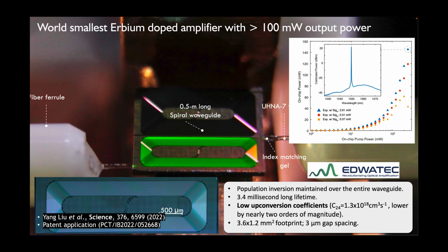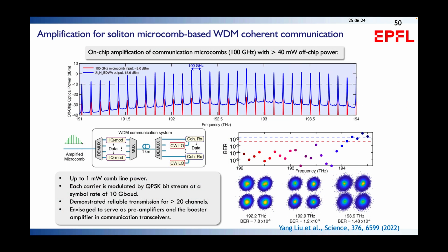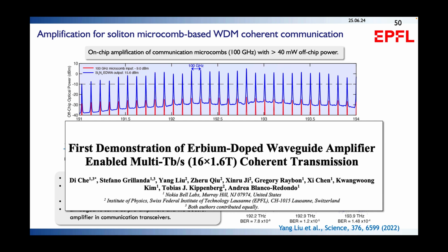Now, where could you employ such very compact Erbium amplifiers? One application is pluggable optics for data centers and data center interconnect, where also you need to amplify the optical signals inside a very small package. One example, from joint work that we did with Nokia Bell Labs, is to amplify channels for data communications. Here's an example from my own lab where we show a 100 gigahertz microcomb in red with very low power per comb line, much below minus 20 dBm, so we can't use it for communications. We run it through our Erbium doped waveguide amplifier. We can conveniently push up all the optical modes to more than 0 dBm, so 1 milliwatt. And we've also demonstrated this together with Nokia, that this technology can be used for multi-terabit per second optical communications of actual data containing signals.